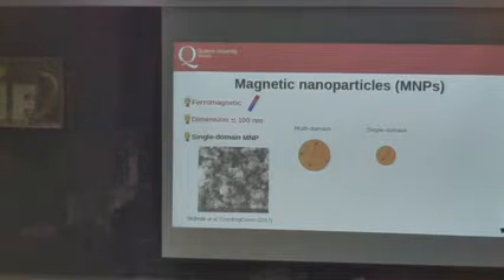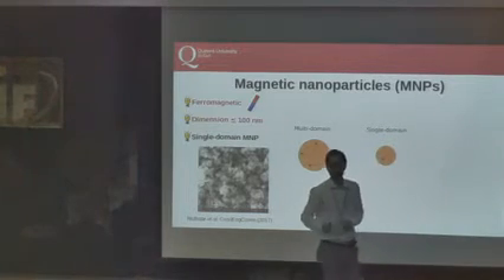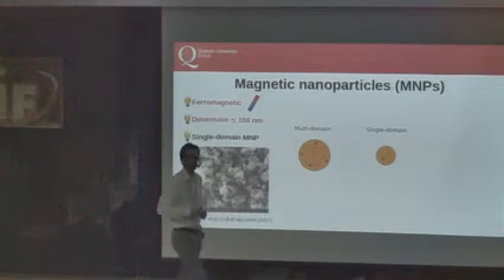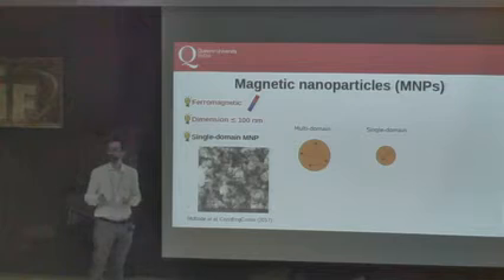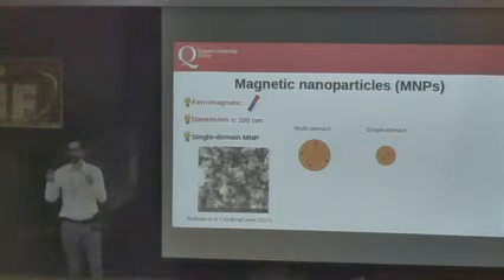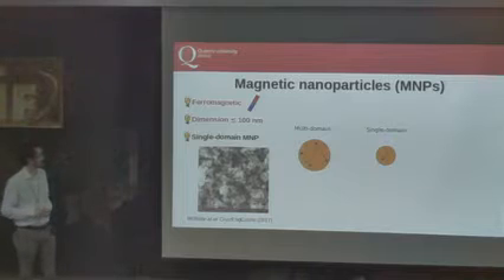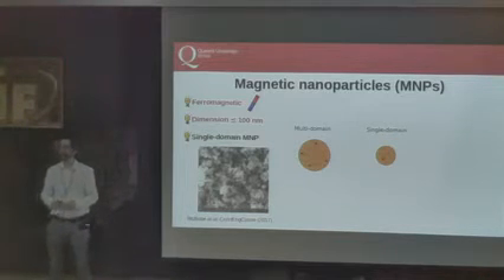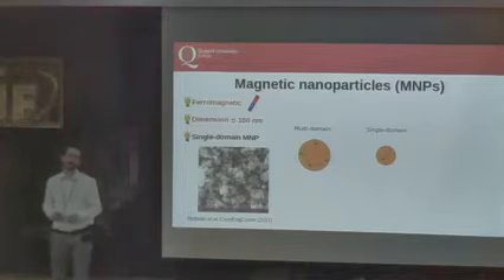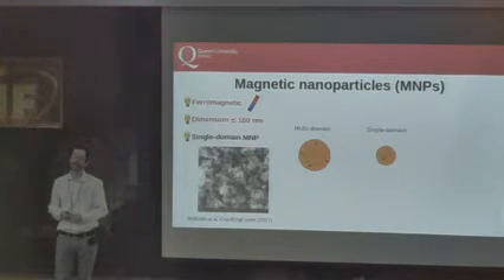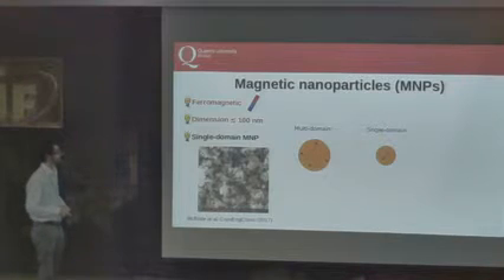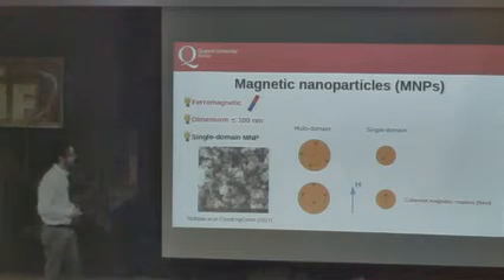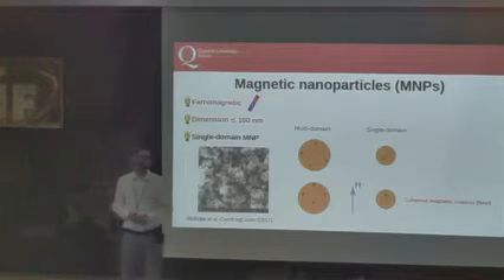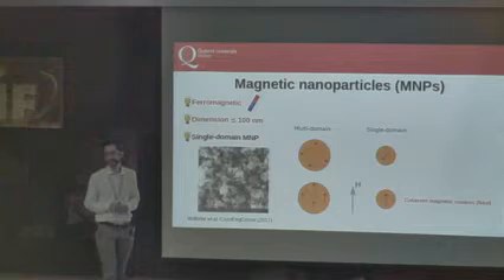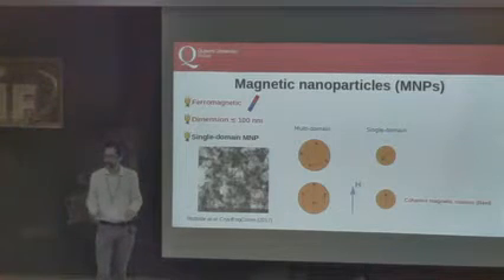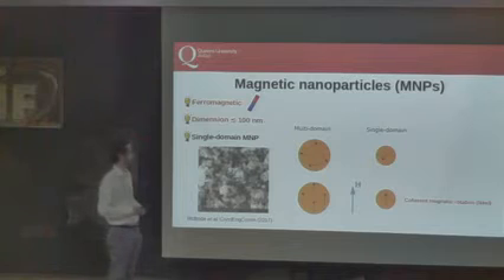One of the most important properties of magnetic nanoparticles, the small ones, is that they are single domain magnets, ferromagnets. What does it mean? Usual magnets are made of several domains with different magnetizations. Single domain nanoparticles are made of a single domain, and we can associate one vector, the magnetization density, to the whole of a nanoparticle. Why is this important? Well, this gives a very determined response of a nanoparticle to, for instance, an external magnetic field or an internal one, as we see later.